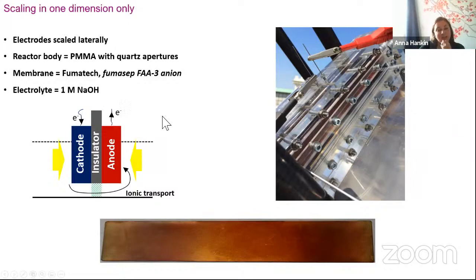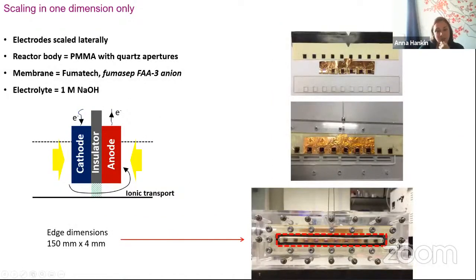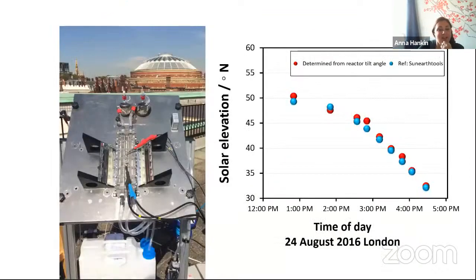And then the next silly bit was that we used triple junction solar cells as the cathode, directly integrated into the reactor. We tried to protect it with some titanium dioxide on top so that they didn't dissolve, but it's definitely an example of a material that tends to corrode quite quickly. But at the same time, it allowed us to carry out a few experiments, and it was the material we had at hand. And so these are some of the results that we got from it.